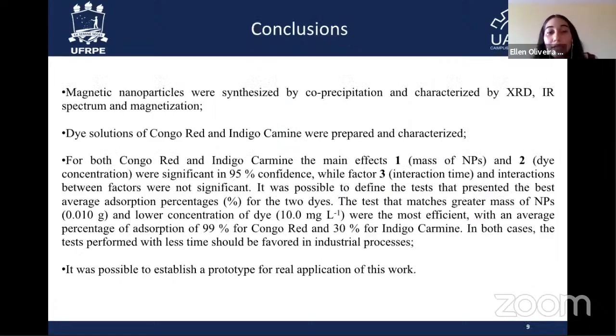As conclusions, we have that the magnetic nanoparticles were synthesized by co-precipitation and characterized by XRD, infrared spectrum and magnetizations. The dye solutions of Congo red and indigo carmine were prepared and characterized. For the Congo red and the indigo carmine, the main effects were only the mass of nanoparticles and the dye concentration at 95% of confidence, while the time and the interaction between factors were not significant.